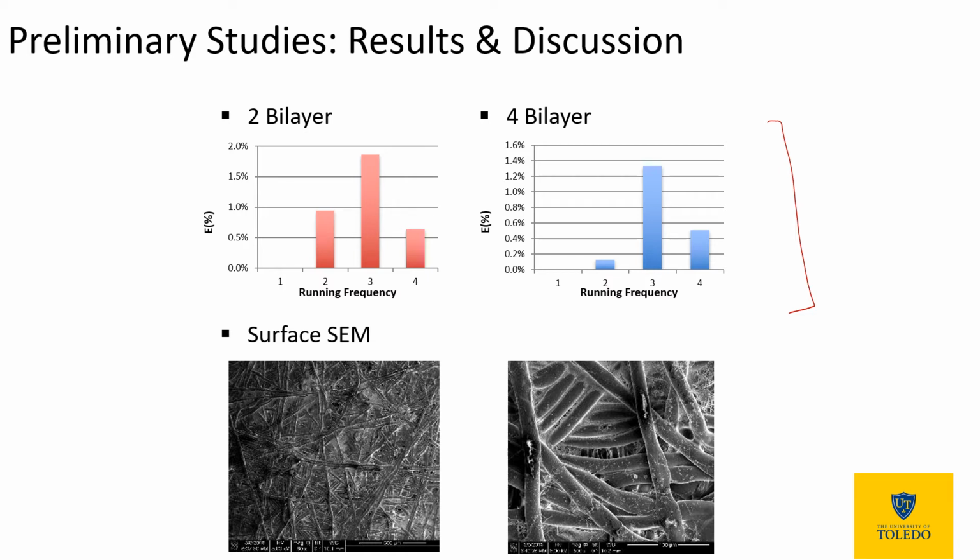And what we see is that we had very small, if any, measurable enrichment. And the reason for this is that the polymers didn't really enter into the pores of the fiber. They deposited primarily onto the surface, as you can see in the SEMs down here below.